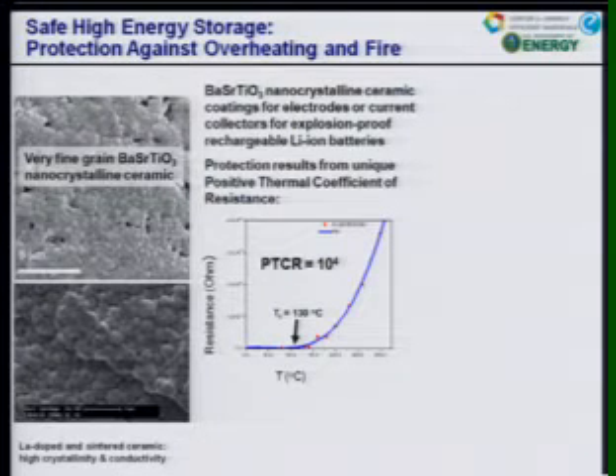Now, the reason this is useful is we're exploring the development of this material as a thin ceramic film to be coated on the electrode or current collector of lithium-ion batteries to make them explosion-proof and fireproof. It's essentially providing a fuse. Because of the way in which we've annealed and doped this material, we find that it starts out with very low resistivity. In other words, it's a semiconductor. It's conducting electricity. When heated above a certain temperature, the Curie temperature, here 130 degrees centigrade, the resistivity increases 10,000-fold. It switches from being a conductor to an insulator. It becomes like a fuse.